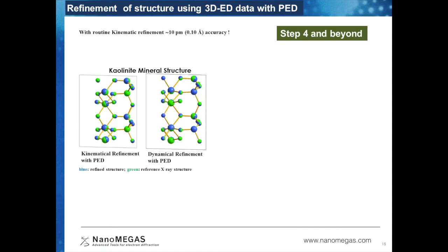As you have seen in all the previous slides, all the structure solution and structural refinement was done in the kinematical approximation, assuming kinematical intensity. With this, we can get quite accurate structures, with 10 picometer accuracy, which is mostly what is required for most structural problems. But one can go a step further to improve the quality of the structures by doing dynamical refinement, which I will not discuss in this presentation due to time constraints. But let's see an example to understand the difference and what we can obtain with dynamical refinement.